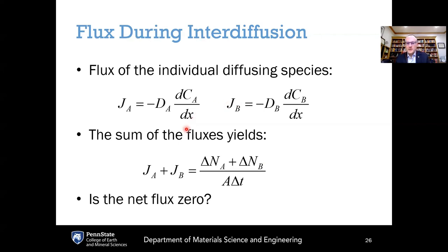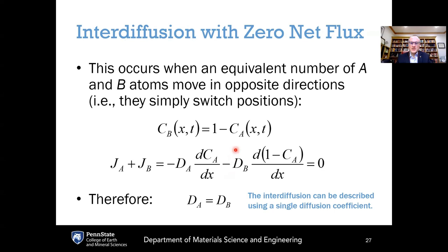And now if we have the sum of the two fluxes, JA plus JB, that can be equal to, say, the change of the number of A plus the change of the number of B divided by the area times the time step. And the question is, is this net flux zero? If the net flux is zero, what that means is that the total concentration is always the same, because A and B are just swapping positions with each other. That means that the concentration of B is equal to 1 minus the concentration of A. So if you add them up, you always get 100% of the concentration here.